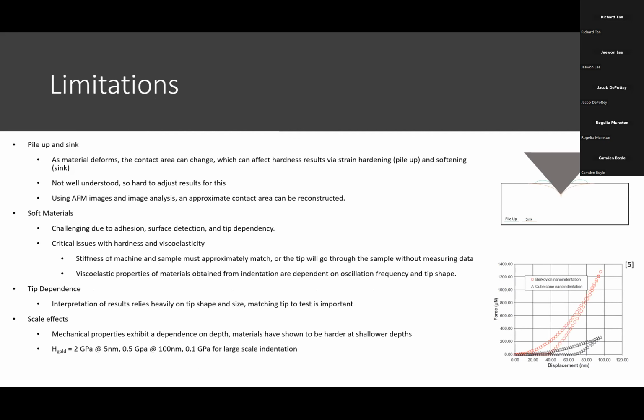Finally, the limitations of nanoindentation. The first is something called pileup and sink. As material deforms, the contact area can change with the tip, and this affects the hardness results via strain hardening and pileup, and softening and sink. The way this happens is not well understood, so it's hard to adjust your results for it. The typical way people handle this is using AFM plots and image analysis, where you can approximate the contact area present during the test.